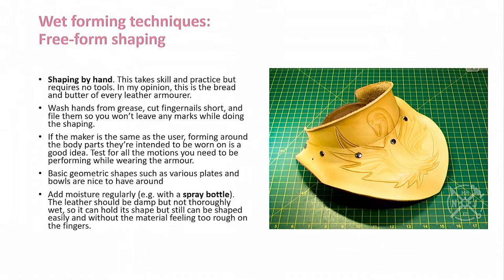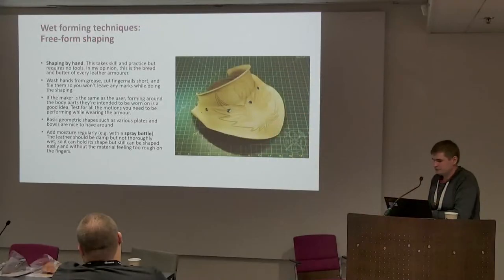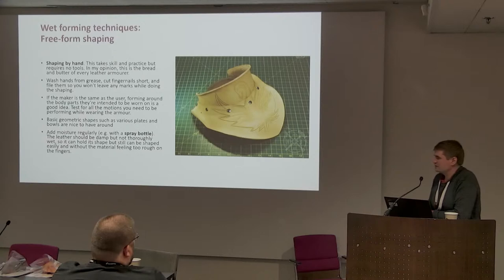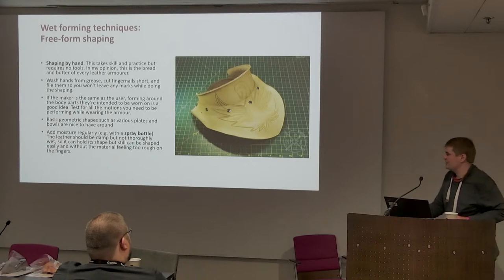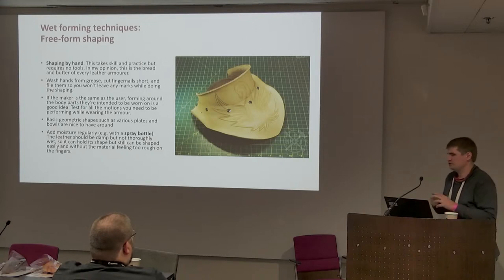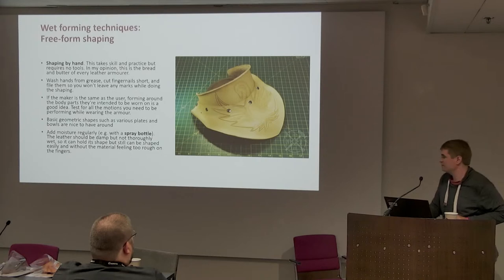So many times when you go to see tutorials about shaping leather or making leather works, you see these tips that you should immerse the leather in water for 5 minutes or 10 minutes or so. That is absolutely wrong. You don't want to do that, it will get too wet. I made some tests and around 1 to 2 seconds is the correct amount for leather with a thickness of around 3 or 3.5 millimeters. It depends also on which section of the hide it is taken from. If you have belly, it will get too wet very soon. If you have bend, you will need to wet it regularly as you shape it.